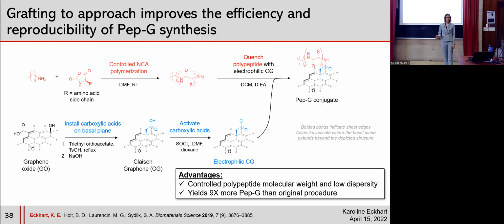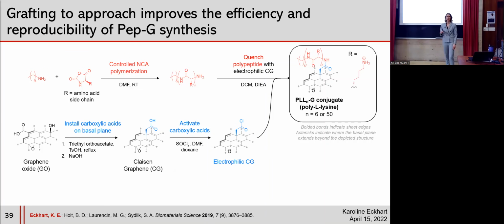And the result of this switch in the chemical synthesis was that we were able to create PepGs where the molecular weight of the peptide was controlled and the dispersity was low. And we also were able to yield 9 times more PepG material than the original procedure. And we made a bunch of different types of PepGs with lysine and glutamic acid. We made block copolypeptide PepGs and random. But the one that I'm going to be talking about today is PLLG, which is poly-L-lysine G.